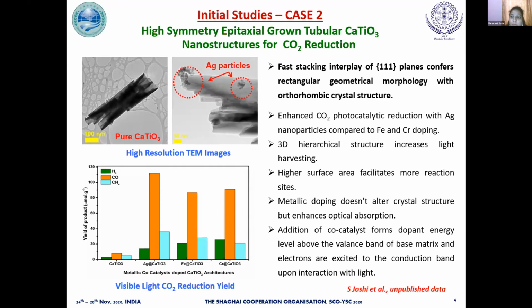Here, the metallic dopants used did not alter the crystal structure, but on the positive side, they enhance the optical absorption by fine-tuning the band gap. Although the results were exceptional, these results are only good from a publication point of view. If we see commercialization plans, a few drawbacks such as difficulty in forming good quality thin films as well as photocorrosion really hindered our plans for commercialization.